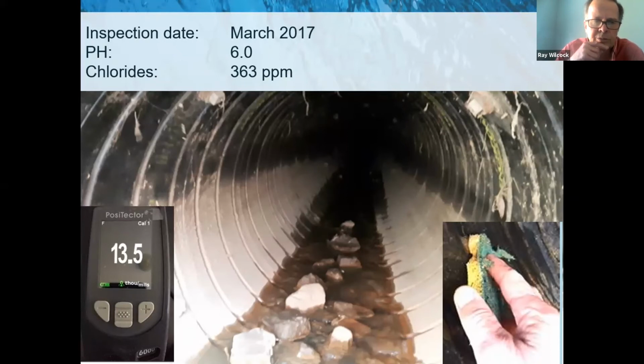And I checked it with my PosiTector down around the invert just to see what it was. It came up about 13.5 mil, and the coating of a polymer laminated pipe is anywhere between a minimum of 10 up to 13, 14. So that pipe was in excellent shape, but you can see some of the stuff that's lying in the bottom, the rocks that could cause some abrasion and also the very corrosive water.